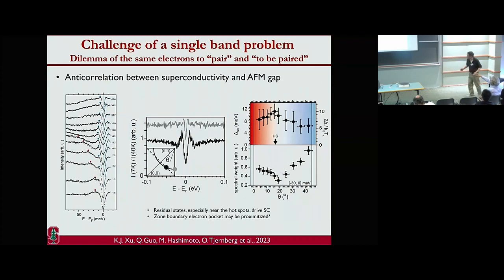Theta equals 45 is the nodal point. Theta equal to zero is the antinode here, and 45 is the node. The node in this sample is being gapped by the antiferromagnetism. It doesn't seem to go to zero at the node. Correct. It's not a superconducting gap, because you don't even have the Fermi surface, because the Fermi surface sinks below at the node. But as you increase the doping, the node gets recovered because you have a Fermi surface.